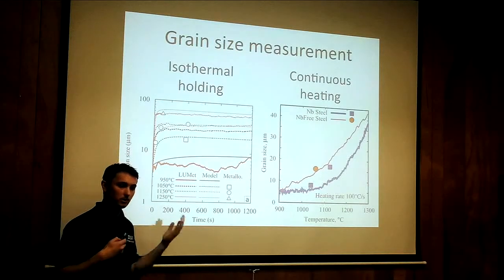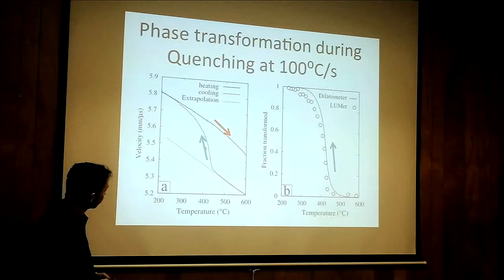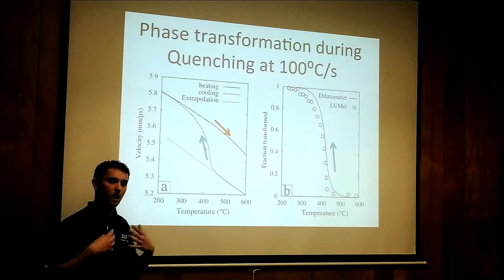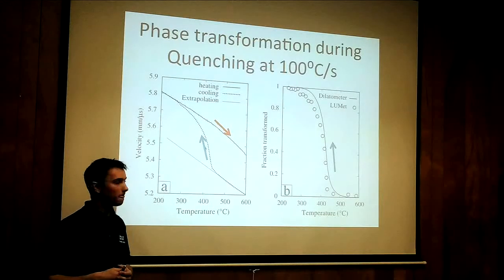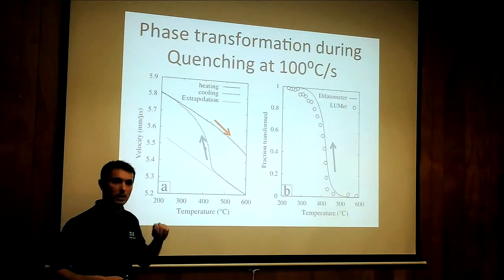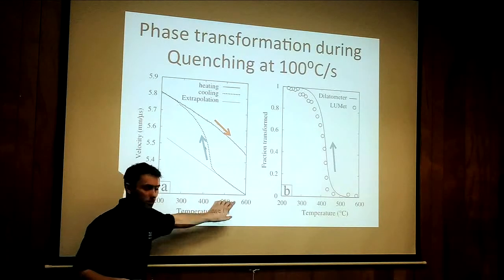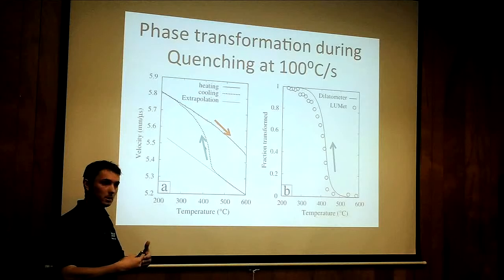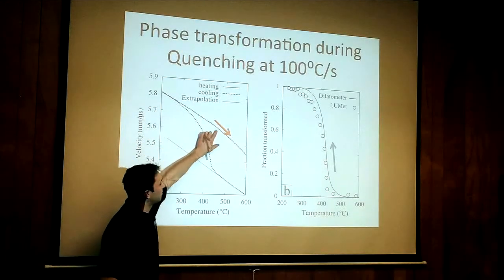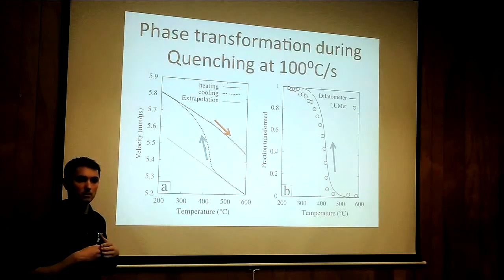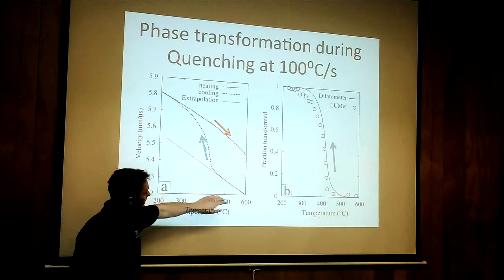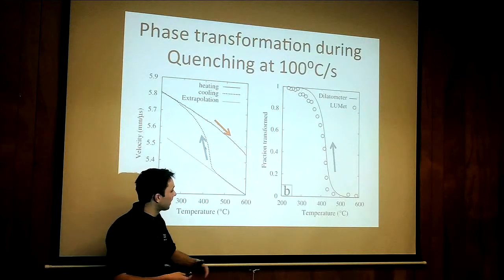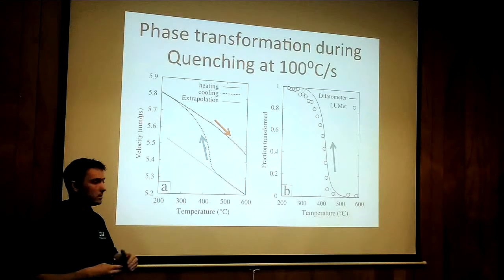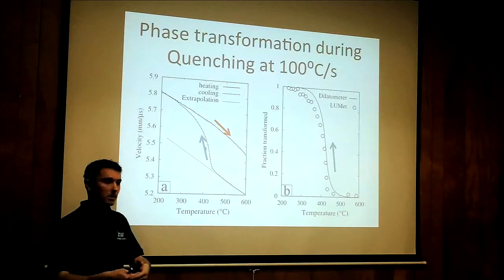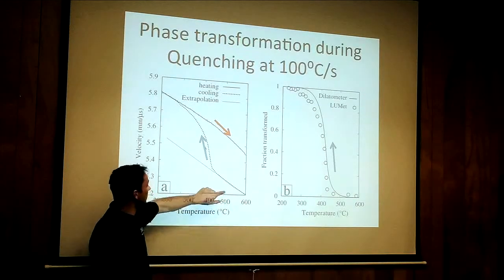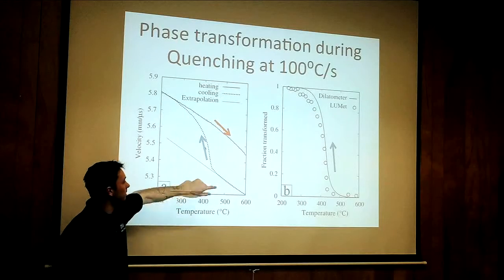Now I'd like to make use of this additional value, the velocity. The velocity is going to be telling us a little bit about how the bulk elastic properties are changing during a treatment. What we see on this graphic here is the variation of the velocity with respect to the temperature as we heat up a steel plate. Upon heating, the velocity is changing non-linearly because this steel has some magnetic properties. And then as we are going into this phase called austenite, at high temperature, the velocity is going to be much lower. As the steel is being cooled down, the austenite will retransform into ferrite, and we can monitor this upon cooling thanks to this curve.